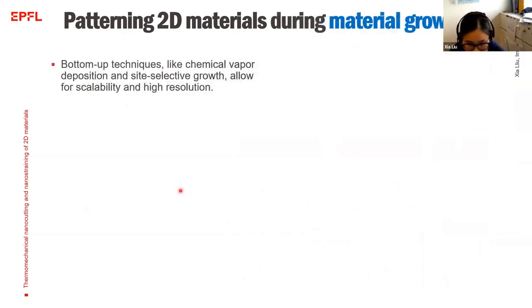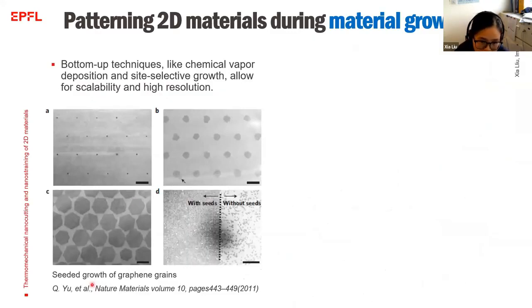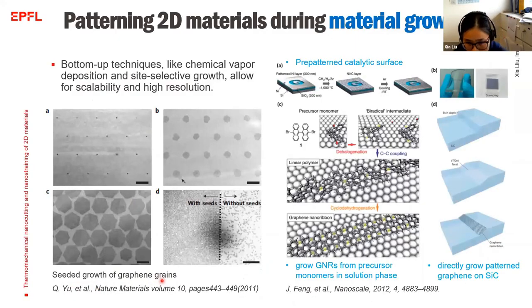So besides the conventional and the laser, some bottom-up techniques have advantages for scalability and high resolution. For example, in the material process, you can introduce the patterning during the growth, such as the seeded growth of graphene, and later the graphene nanoribbon or graphene pattern during the material growth. But this method cannot fabricate a very complicated device structure. If you want to design another pattern afterwards, you cannot do it because it's designed during the material growth.